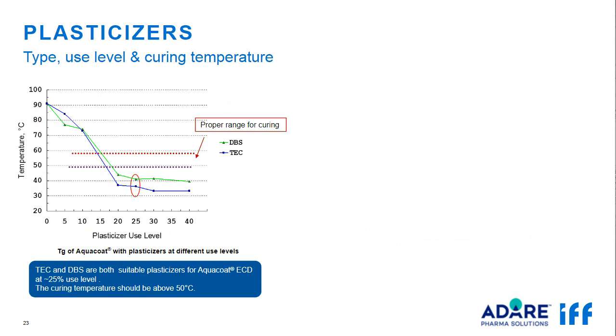Ethylcellulose has a glass transition temperature, or Tg, of 91 degrees centigrade. It is very rigid at lower temperatures without plasticizers. With the addition of about 25% plasticizer to the coating formulation, the Tg reduces to 35 to 40 degrees centigrade. At this temperature, the solid particles can deform to coalesce and form a continuous and ductile film surrounding the substrate.